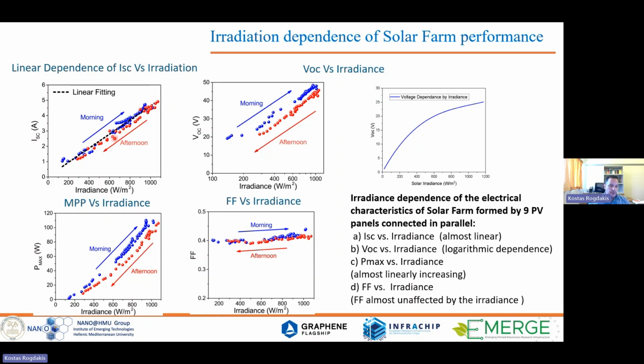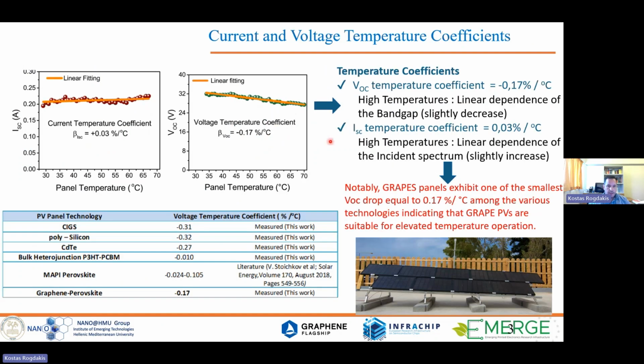Okay, so these are typical measurements through the course of the day of the park and the panels. We also measured hysteresis between morning and afternoon. So usually during the morning we have better performance compared to the afternoon performance. Another highlight was to extract the thermal coefficient for the current and the voltage from these curves.